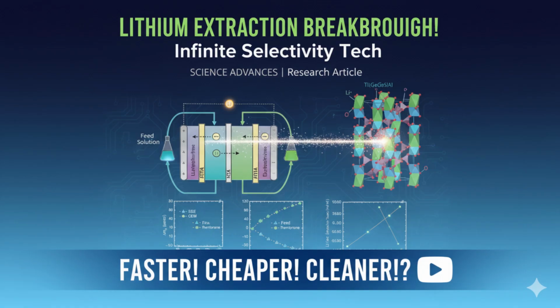So it's a combination of size and charge and the energy needed to shed water. It's multi-factor security. Precisely. It's this unique combination enabled by the solid-state transport mechanism that leads to that immeasurable selectivity they observed. No detectable sodium, potassium, magnesium crossing over. That is genuinely remarkable. But you hinted earlier, or the outline did, about a trade-off. Even if these other ions can't get through the membrane, their presence can still cause issues.